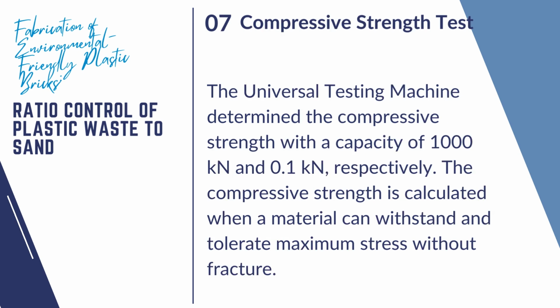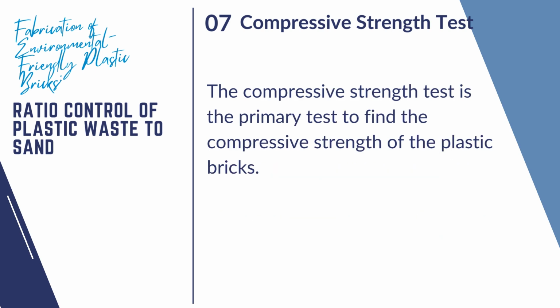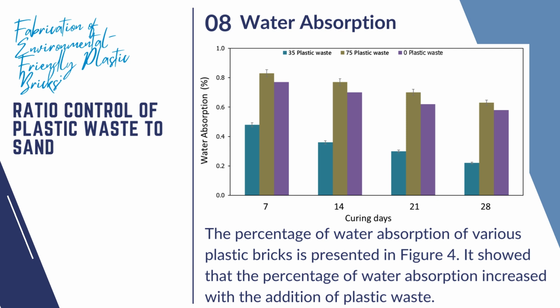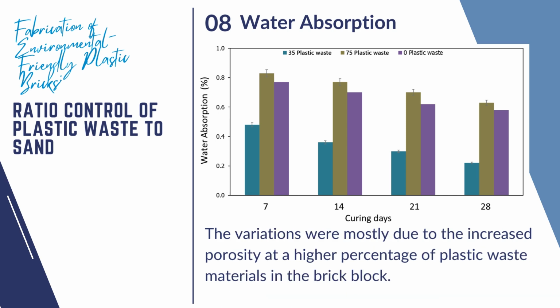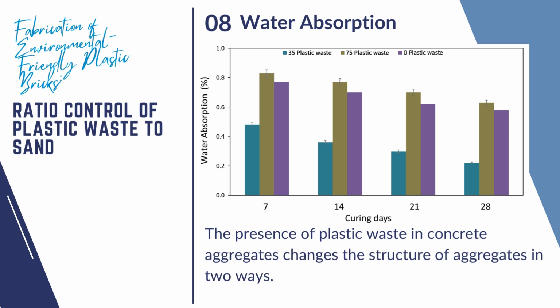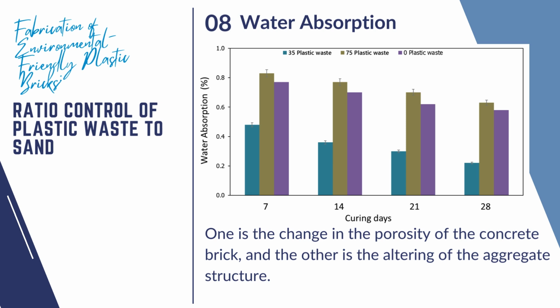The universal testing machine determined the compressive strength with a capacity of 1000 kN and 0.1 kN, respectively. The compressive strength is calculated when a material can withstand and tolerate maximum stress without fracture. The compressive strength test is the primary test to find the compressive strength of the plastic bricks. The percentage of water absorption of various plastic bricks is presented in Figure 4. It showed that the percentage of water absorption increased with the addition of plastic waste. The variations were mostly due to the increased porosity at a higher percentage of plastic waste materials in the brick block. The presence of plastic waste in concrete aggregates changes the structure of aggregates in 2 ways. One is the change in the porosity of the concrete brick, and the other is the altering of the aggregate structure.